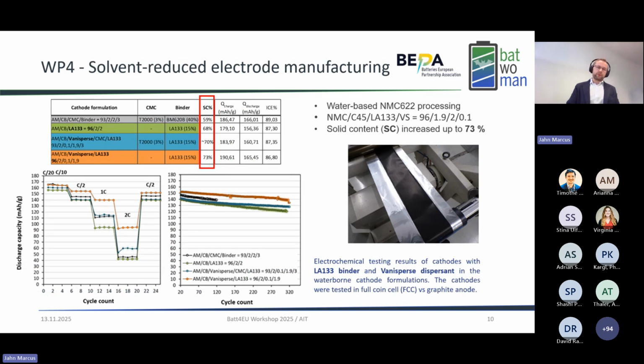Work package 4, so this is one of the more technical or experimental work packages. Here we tried essentially solvent-reduced electrode manufacturing. With the traditional water-based electrodes, so we used an NMC622, as I said before, so we went water-based right from the start. However, when you do that, we only achieved a solid content of 59% in the slurry. And as you know, this is not particularly high, but as you go to water-based, you tend to have a lower solid content compared to NMP, which is an issue.